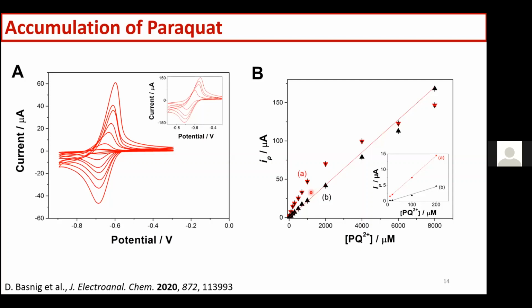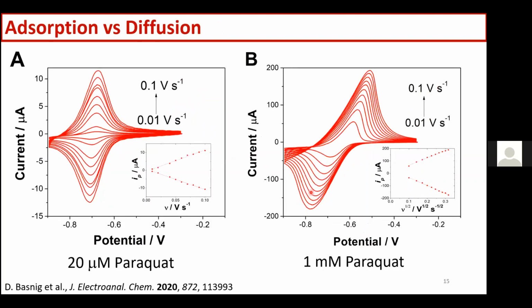And then we could verify this by doing some cyclic voltammetric studies and scan rate studies, and you can see that at the low concentration of 20 micromolar, we do have adsorption behavior with a peak-to-peak separation of 10 to 20 millivolts, and the peak current was linearly dependent on the scan rate.